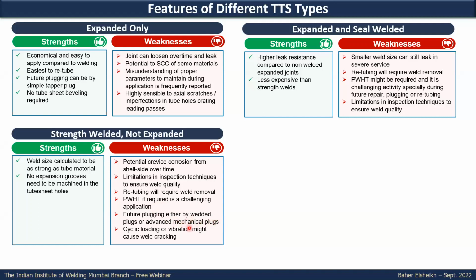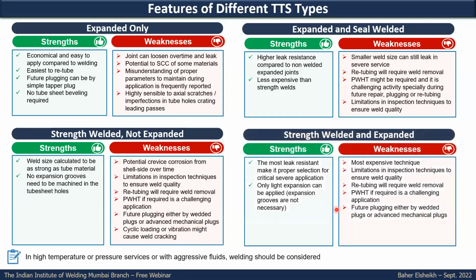You have to either install mechanical plugs or the welded plugs. And under cyclic load, in case you don't have the expansion, this strength weld will be subjected to fatigue cracking, and it might be cracked. The last configuration may be strength weld plus expanded, and this is the most leak resistant one. You will have the strong weld, and you will have also the expansion, which will close the gap.